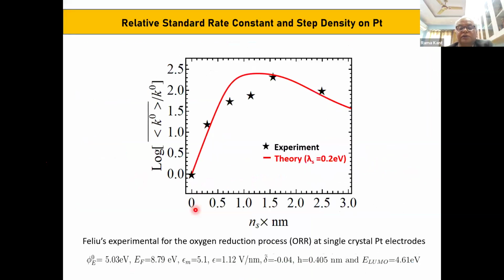And then finally, I'm jumping over a lot of things and coming to an experimental result. Some experimentalist groups created various cut angles and got metal surfaces which varied the step density per nanometer. And they showed the oxygen reduction process, ORR, on single crystal platinum electrodes with various cut angles. This red line is our theoretical line, and these stars represent their points. So something strange is happening in this area, or maybe if they repeat this experiment with their error bars, it is within error also.